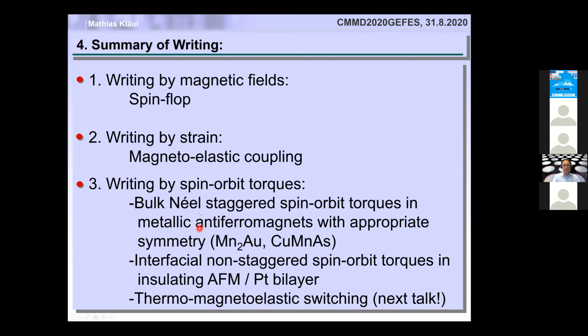So to sum this up, we can now write information by doing spin flop if you have a lot of field, by strain if you have a medieval torture device for samples, or by using spin orbit torques, in particular bulk spin orbit torques in these special materials with particular symmetry, or interfacial non-staggered spin orbit torques in insulating systems, and finally also thermo-magnetoelastic switching, and see the next talk for all the details on that.